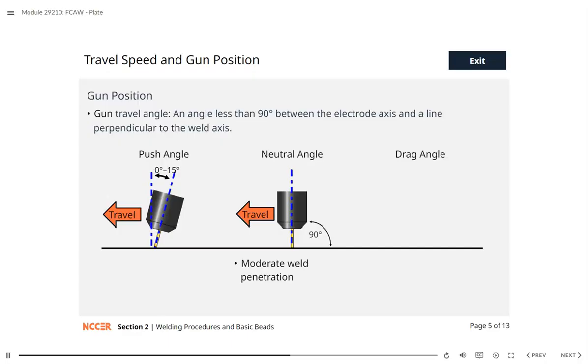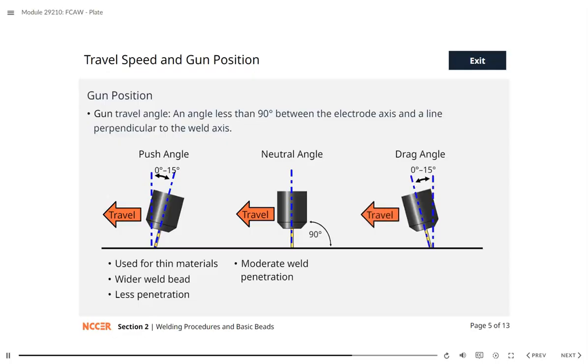A push angle, which is typically used for thin materials, is created when the welding gun is tilted back and the electrode tip and shielding gas move ahead of the weld bead. This type of travel angle creates a wider weld bead with less penetration. A drag angle is created when the welding gun is tilted forward and the electrode tip and shielding gas move back toward the weld bead. This type of travel angle creates a higher and narrower weld bead with maximum penetration.